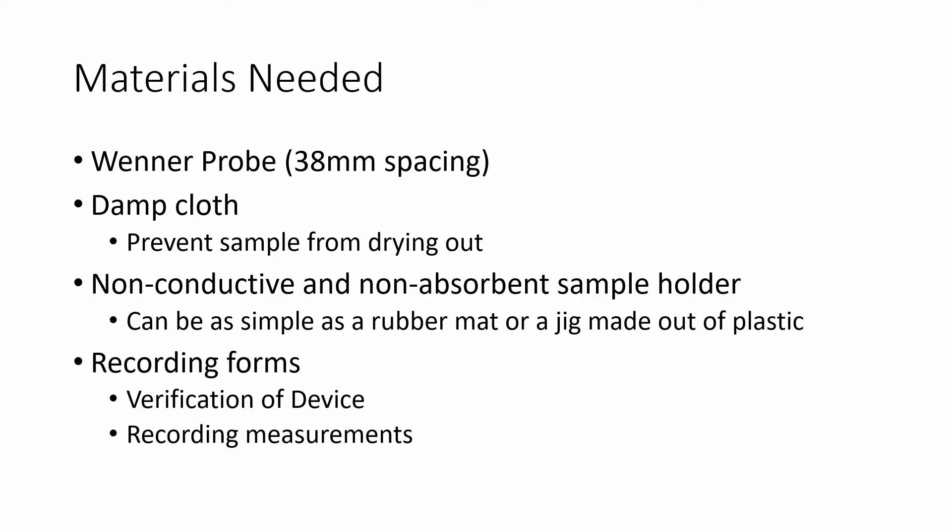Here are the materials that you are going to need to perform resistivity testing. You will need the Wenner probe at 38 millimeter spacing. You also need a damp cloth to prevent the sample from drying out. You also need to obtain a non-conductive and non-absorbent sample holder — this can be as simple as a rubber mat or a jig made out of non-absorbent or non-conductive materials. You will also need recording forms: one to verify the device is working properly, and a way to record the surface resistivity measurements from the probe.